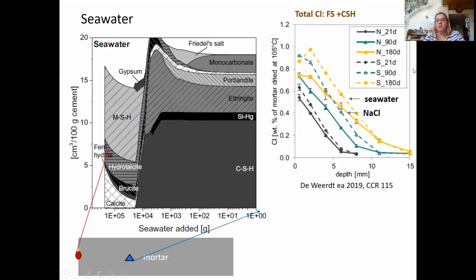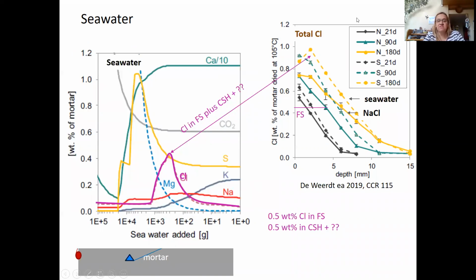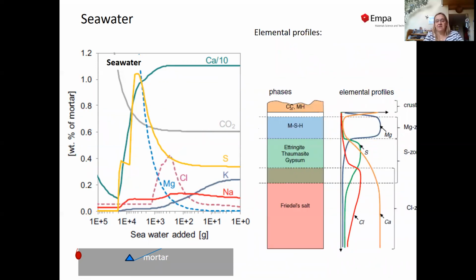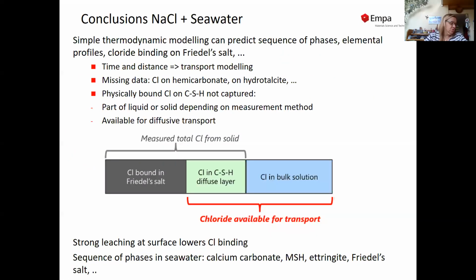And if we now compare it to our chloride ingression measurements, we can see again, we predict the formation of chloride in Friedel's salt. As discussed before, it's not only Friedel's salt, but also CSH, possibly some other phases which bind it. And we see a clear decrease, basically because we start to form the other phases like ettringite and eventually monocarbonate, M-S-H. And again, as already said before, the changes predicted by thermodynamic modeling agree quantitatively very well with changes observed in seawater exposed samples. So to conclude this part, simple thermodynamic modeling can predict the sequence of phases, elemental profiles, and the chloride binding on Friedel's salt.